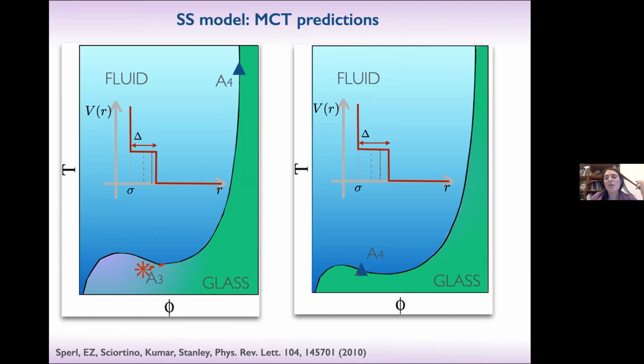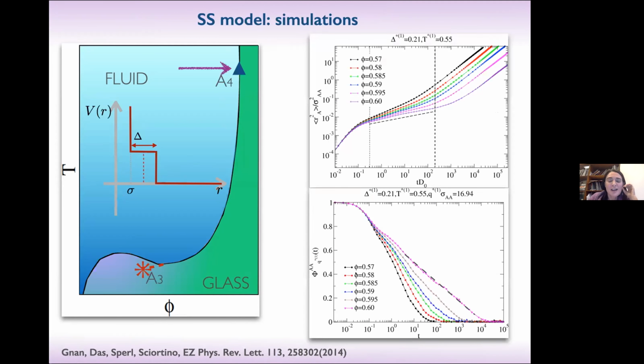And so what we did in Rome was to test this by computer simulation, because as I told you, we like to do very, very long simulations in Rome. And so we simulated a binary mixture of square shoulder this time with different deltas. And then I will be brief. I just show you, we chose this path here, approaching the A4 singularity predicted by the theory. And here you see that for this path, at this particular delta and temperature and varying packing fraction, there is the onset of this very long extended subdiffusive behavior in the mean-square displacement, and the onset of the logarithmic dependence of the density correlation function at this particular Q.